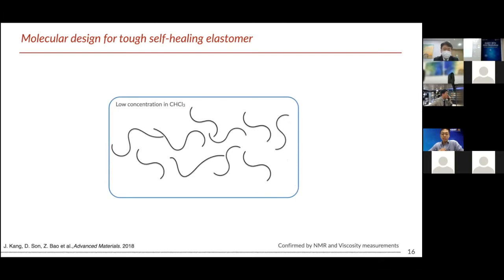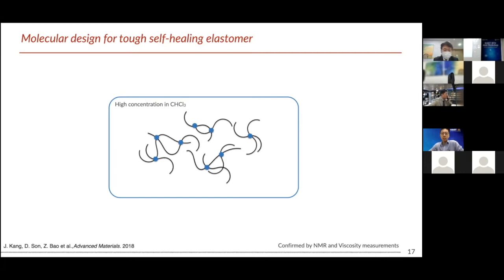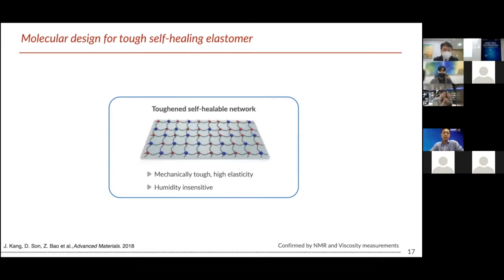So then how can we imagine how they form such networks? In order to prove their structure, we performed NMR experiments and also viscosity measurements. If you want to make the film, first we need to dissolve the polymer in the solvent. At low concentration, they should be highly dispersed and there's no particular physical interaction between the polymer chains. But we found that at a certain concentration, only the strong bond starts to form, and the weak bond is still highly dispersed. Based on this pre-crystalline structure, after full evaporation of the solvent, they eventually make a very interesting self-healable network with two kinds of bonds.